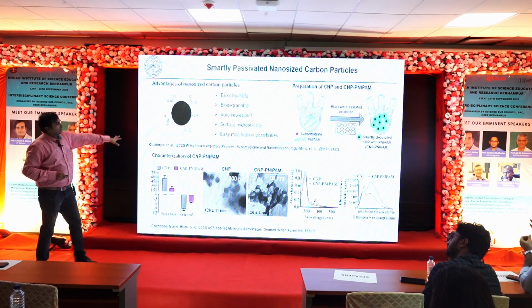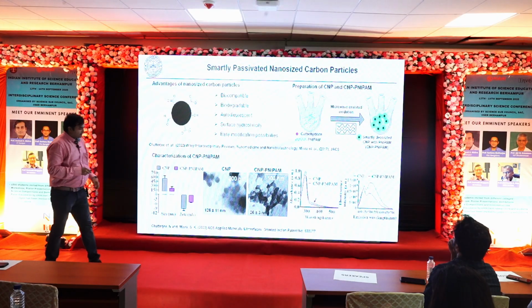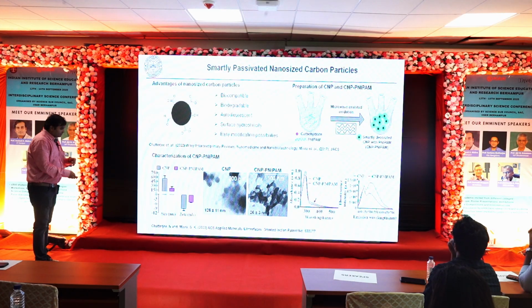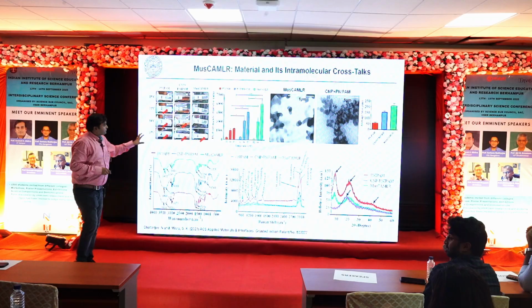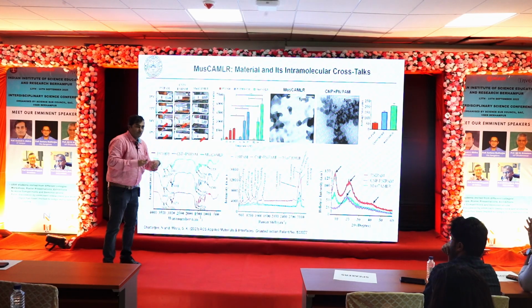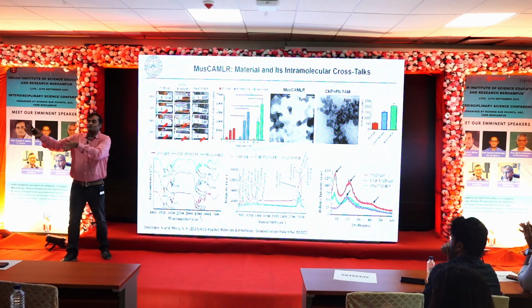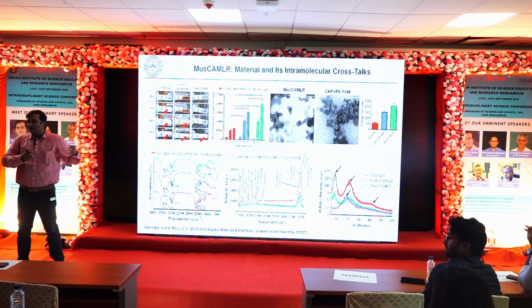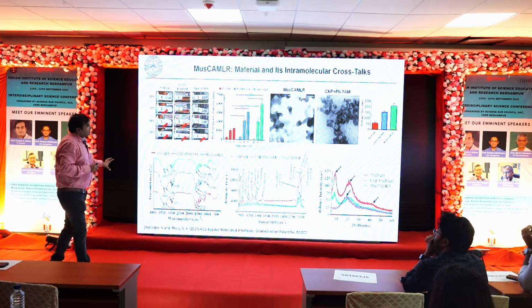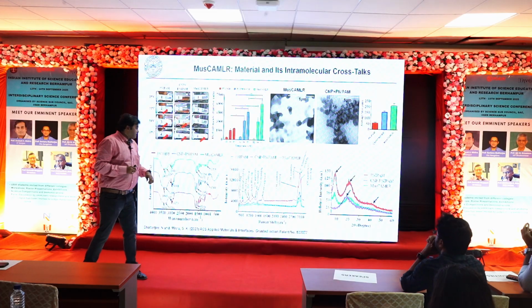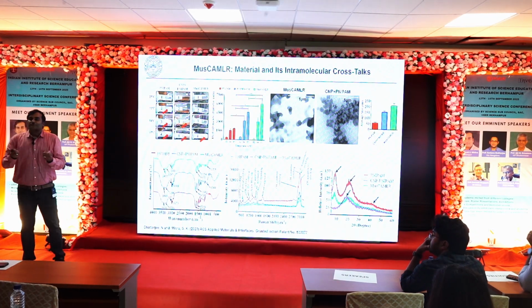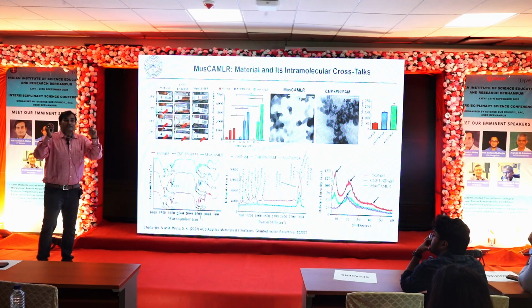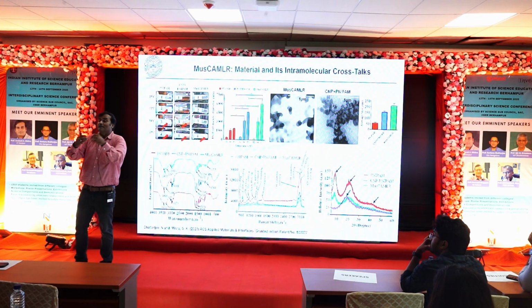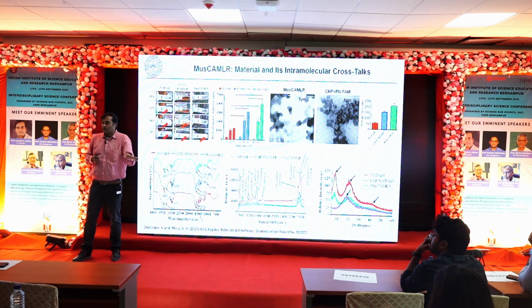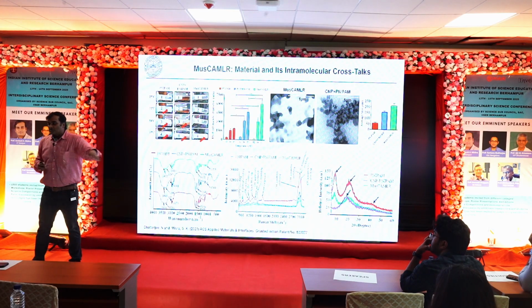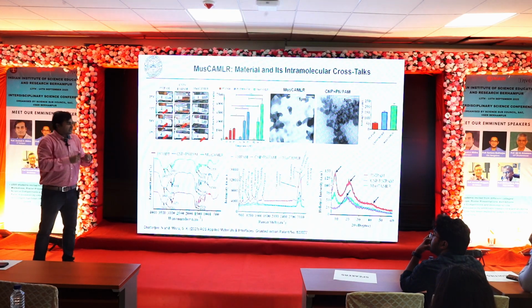So the material was prepared and characterized by different methods. I will not go into the detail. Then we looked at how it is interacting, whether the functional groups on the surface of the carbon particle and the polymer chain are having some interaction or not. Different characterization methods were followed, and we did find that these are not just two dead materials next to each other. Actually they are talking to each other in the presence of water. Whenever there is water in the system, they do talk to each other, they are interacting.